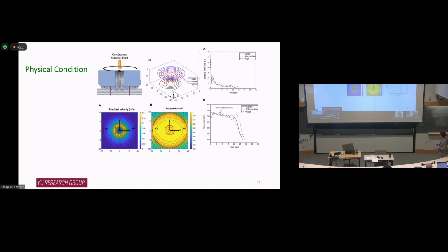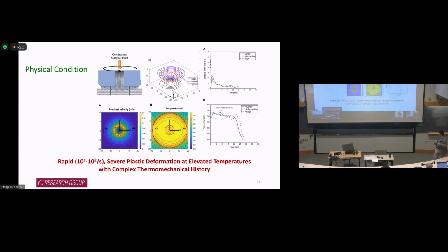But I think the take-home message overall from the in-situ monitoring experiments and from the process modeling is that this is a rapid and severe plastic deformation process in nature. It happens at high temperatures. It's below the melting temperature, but the thermomechanical history is pretty complex. It's not a constant temperature. It's not a constant strain rate. So this is some fundamentals of the process.